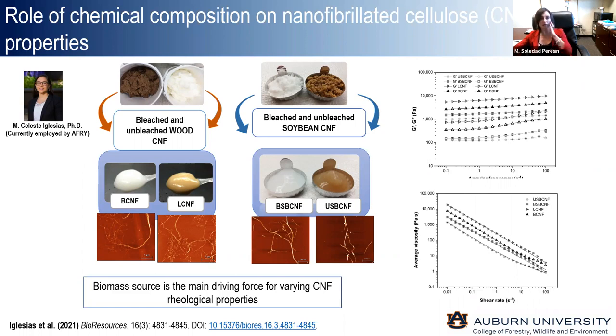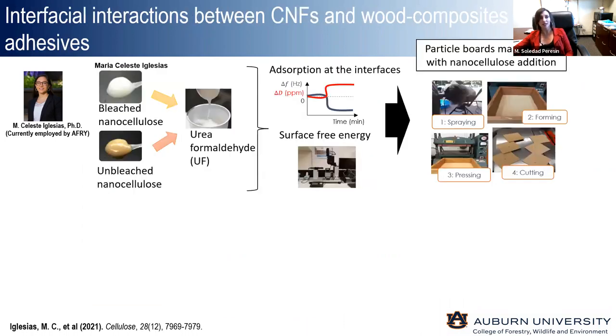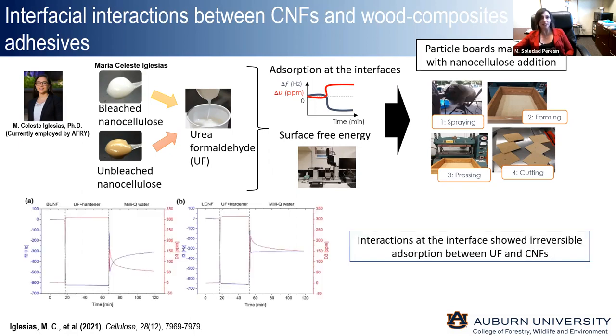So this was kind of a seminal work that we did to understand the impact of this chemical composition on certain applications, as in the case of wood composite adhesives. And what we did in this case, we used our surface sensitive techniques to understand the behavior or the interactions between nanocellulose, completely bleached versus lignin containing nanocellulose, within this case urea formaldehyde resin, to understand how these interactions and the surface free energy were, and try to replicate these or move forward and try to predict their behavior in particle board using urea formaldehyde as a resin.